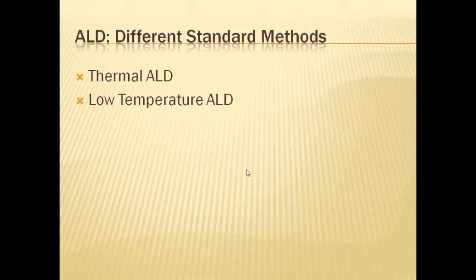However, the same reactions may occur at low temperature as the reactions themselves are highly exothermic. Low temperature deposition is at times required in case a substrate is unable to withstand the high temperature, for example for biologics. In most cases, the deposition rate and quality remains almost the same at low temperatures, but usually the cycle duration increases as a higher time is required for purging to prevent thermal CVD from taking place. Some reactions do not take place at low temperatures or would take a long time. These reactions are enhanced using catalysts, for example silica ALD.